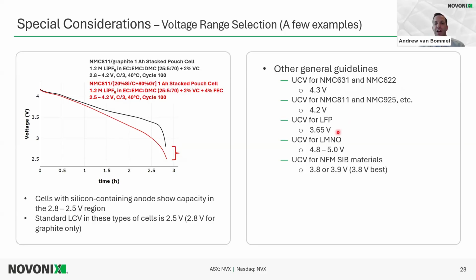For LFP, around 3.65 volts. There's no more capacity after that. For LMNO, we're looking between 4.8 and 5 volts, and we get better cycling when we're at lower voltages, 4.8, 4.9. That's due to less manganese dissolution at that higher voltage.